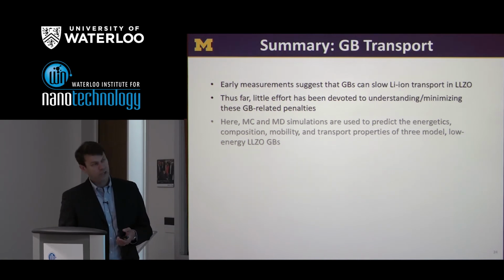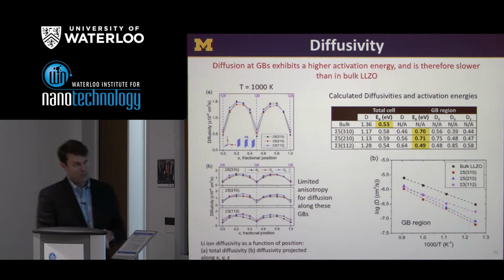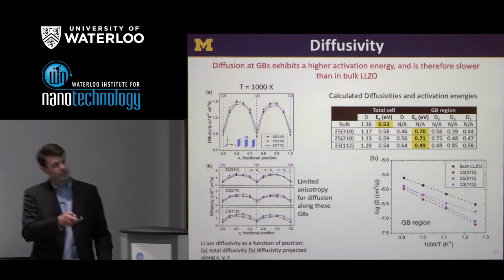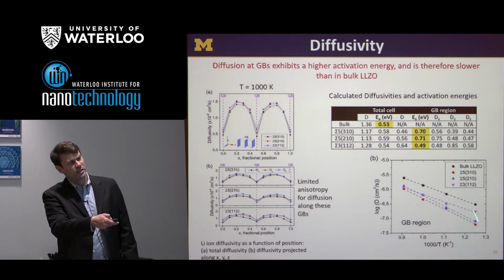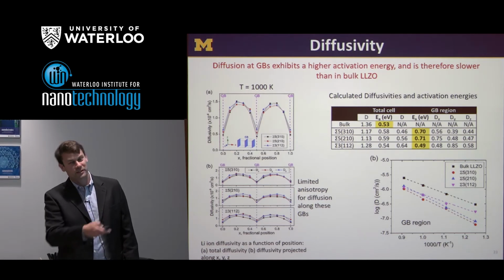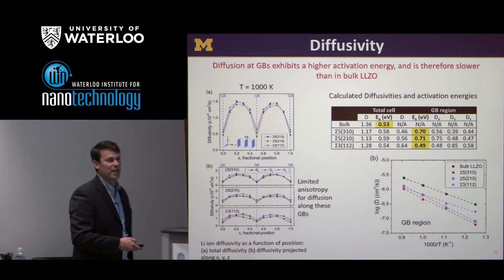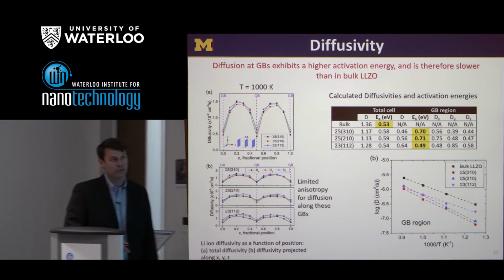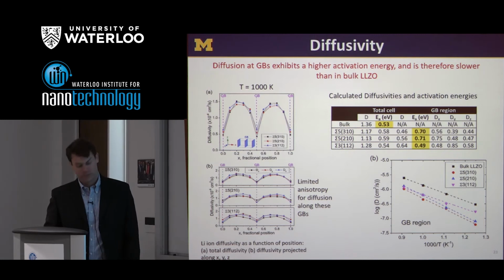So if we can extrapolate, you may say, well, what's happening at room temperature? Of course, we've only looked at high temperature in these particular calculations, but if we were to extrapolate these out to room temperature, I would expect that there would be a much bigger difference or a bigger penalty associated with grain boundary diffusion at those low temperatures.